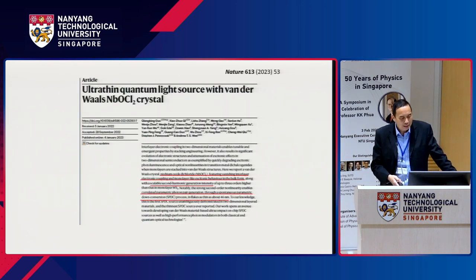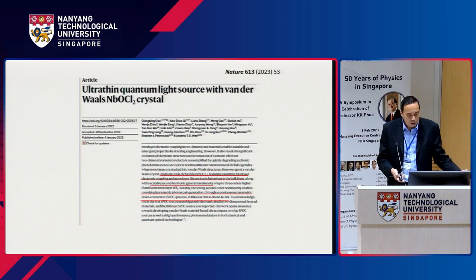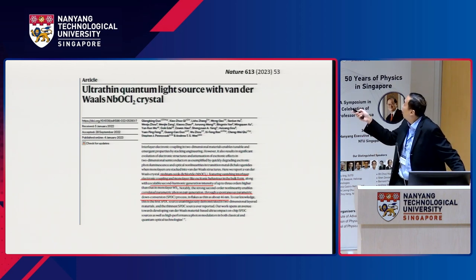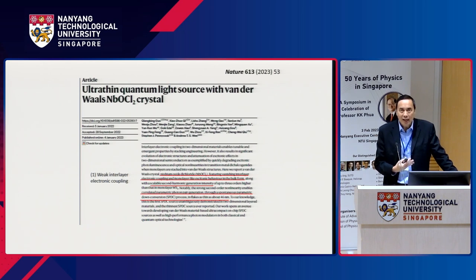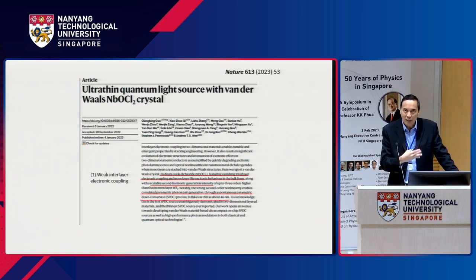And this is some of our recent work done by a very good RF, Kuo Changping. He's working on a different 2D material, this time a non-centrosymmetric 2D material, niobium oxide dichloride. And the essential difference about this material is that it has weak interlayer electronic coupling, which is unlike the TMDs. Because they have strong electronic coupling, you will have different band gaps with different numbers of layers. In this case, the bulk also behaves like the monolayer. So this is one property which makes it different.